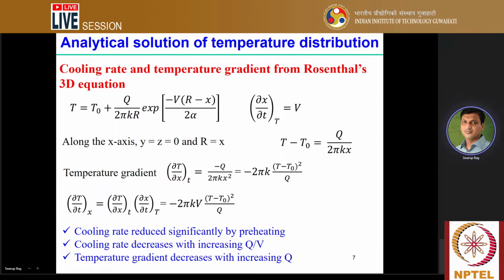The third conclusion here is that temperature gradient decreases with increasing Q. Temperature gradient, del T by del X, we have already calculated, and we can see that it decreases with increasing Q. Here in the equation you can see minus twice pi k (T minus T0) squared divided by Q. I'm talking about the magnitude, neglecting the sign convention here. So don't consider the sign, just focus on the magnitude of this value. So as Q increases, the temperature gradient decreases. These are the kinds of inferences we can derive from this particular expression.